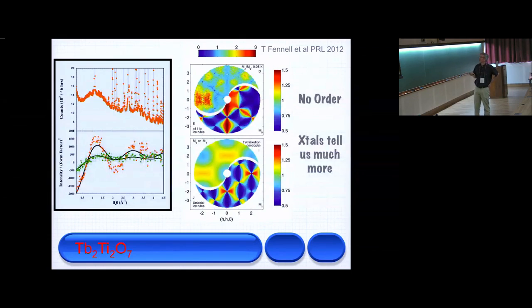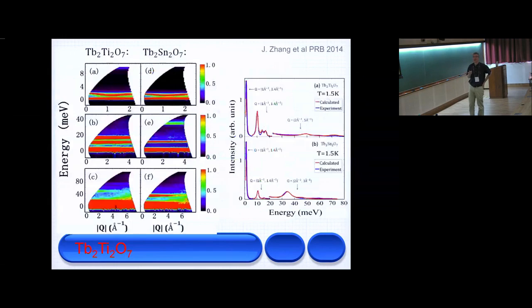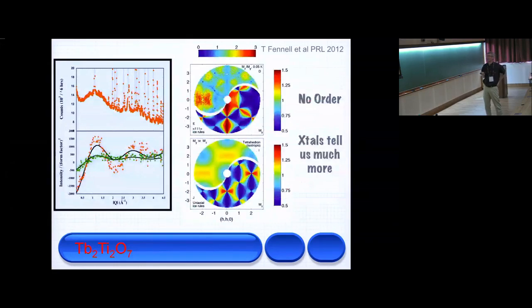So these are the crystallographic axes. So this is HH and this will be L planes. And there's different components of the magnetization from polarization analysis. We can talk about it later, but Tom Fennell did that in 2012, so it's some time ago, in terbium titanate. And really, I could take spin ice or really any material, a powder. In neutron scattering, inelastic neutron scattering is a 4-dimensional problem. With a powder, you take the X, Y, and Z down to a mod Q, just a length scale, and then you can get energy, so you could have 2. In this case, it's just diffraction, so you're only looking at 1.